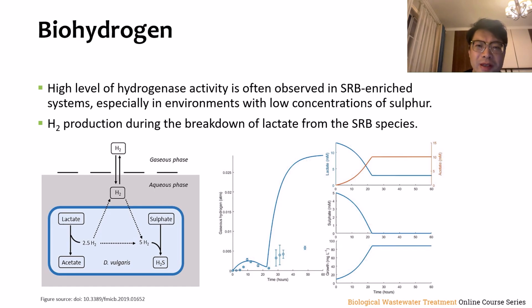This rate increased nearly tenfold to 5 millimole per liter per hour using a sparging reactor that maintains low hydrogen partial pressure, optimizing their thermodynamics. Another study identified two main electron transfer pathways in Desulfovibrio. One is direct electron transfer through periplasmic hydrogenase, and the other is the transmembrane electron transfer method.